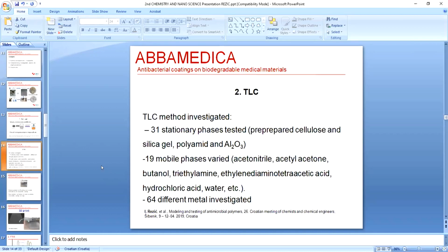And what we have tried to do is develop a chromatography procedure in which we are testing 31 stationary phases and 19 mobile phases. Among stationary phases, we have tested cellulose, silica gel, polyamide, and aluminum oxide. And among mobile phases, we varied acetonitrile, acetylacetone, butanol, triethylamine, ethylenediaminetetraacetic acid, and hydrochloric acid with water and others. As for now, we have investigated 64 different metals.